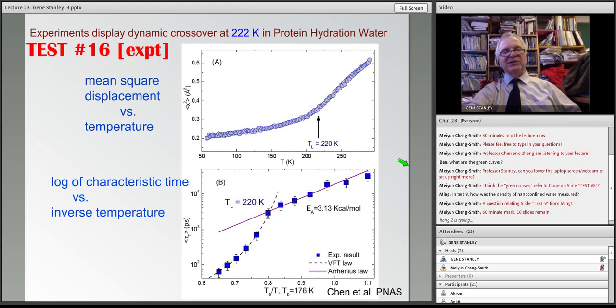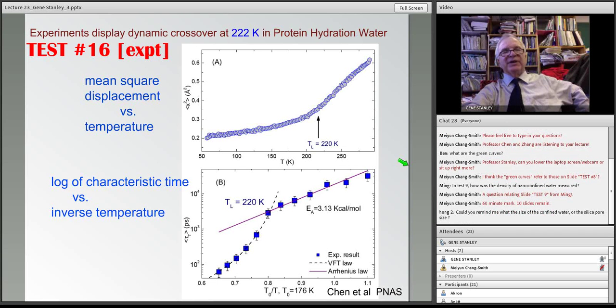In the protein water, this is not confined in glass, silica glass, but it's confined by protein. And very recent results from the Chen group show that you don't even need a biological molecule. You can do these experiments all over again in cement. Everyone knows that water finds its way into cement, and it's of course confined on a very small scale. That's why it doesn't freeze. And you can go down at low temperatures and make these same measurements on cement, water confined by cement, and you get the same curves.